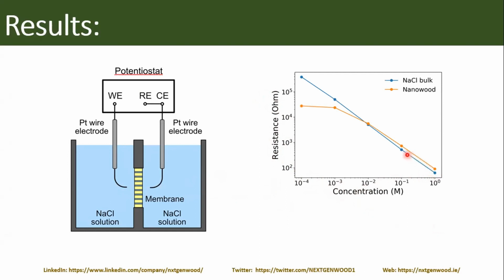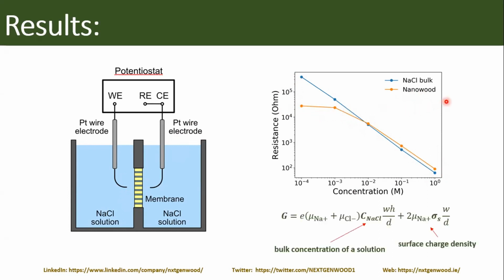And if we first look at sodium chloride electrolyte, bulk electrolyte, so there is no membrane in here, we see that it's a linear relation and what it should be. And if we make the same experiment with Nanowood, we can say that first at very high concentrations, we see quite similar behavior, and that at a certain point, somewhere here, we see that the curve goes in a different way. And that's how we explain it.